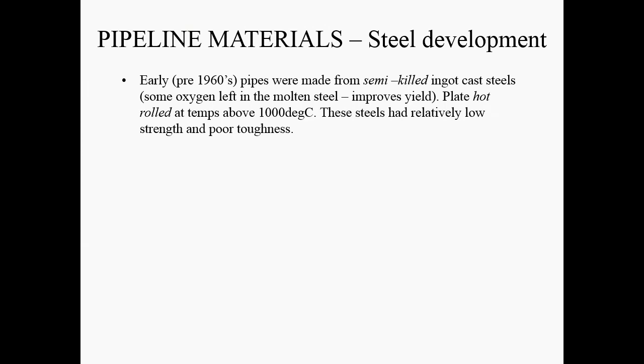But the steel didn't have particularly good properties. The plate was hot rolled, so you take an ingot, which is a three-dimensional shape, and you put it through two rollers, and you roll it just like a rolling pin into a slab, and then you roll that slab into a sheet, which you then use for making pipes. The hot rolling process was about 1,000 degrees C.